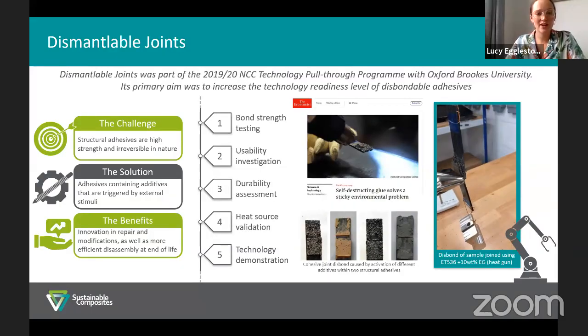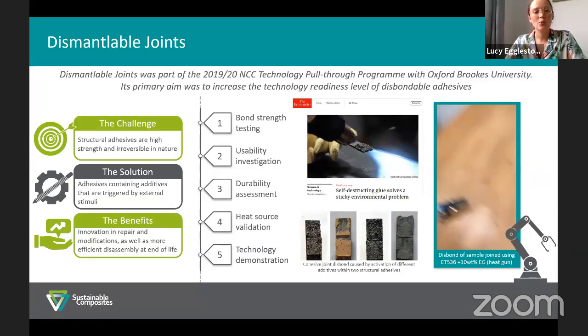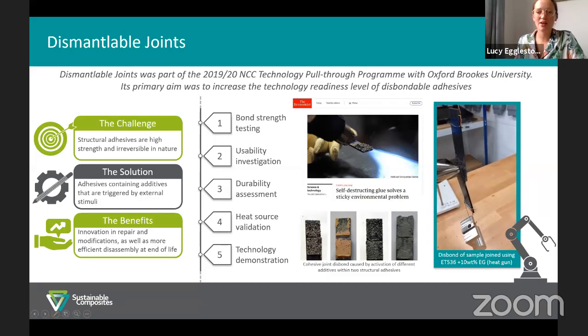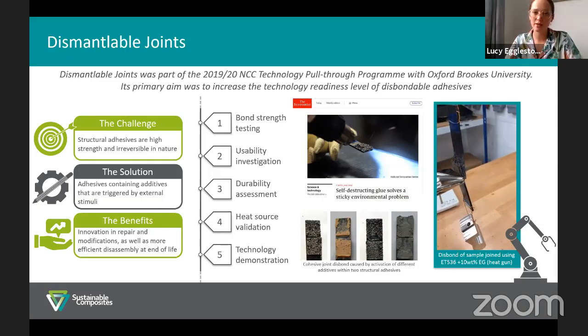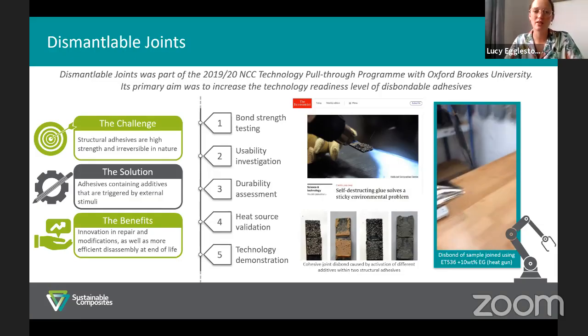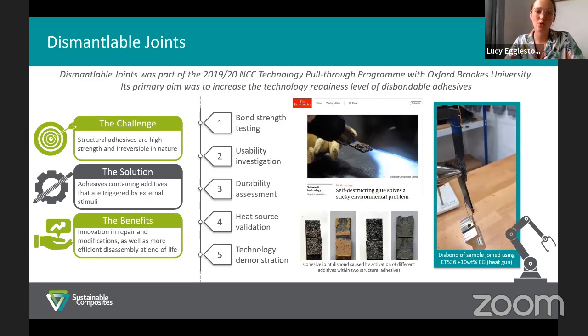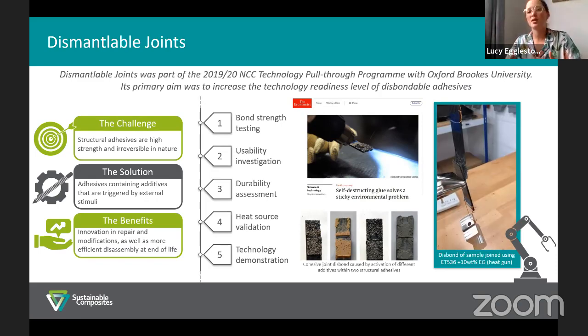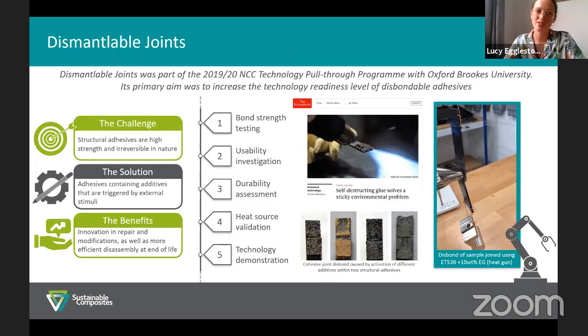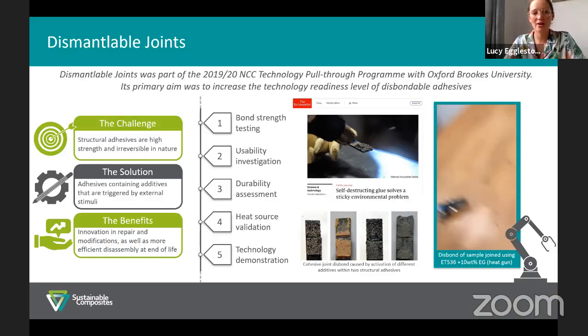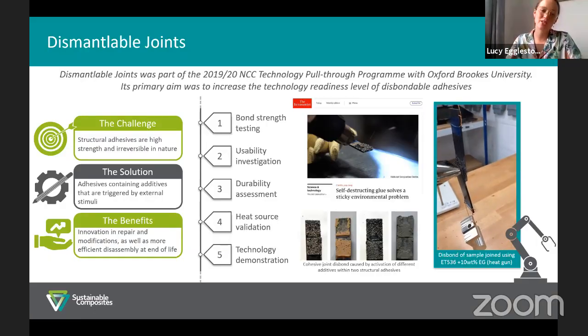So alongside investigating those different heat sources, we tested the bond strength of the joints that we'd created, as well as investigated the usability of the adhesive once they'd been combined with the additives, so that we really got an idea of how usable are these and how easy would they be to just slot into everyday manufacture. Alongside that, we assessed the durability of the joints, and once we had all of that information, we used it in combination to create a technology demonstration.